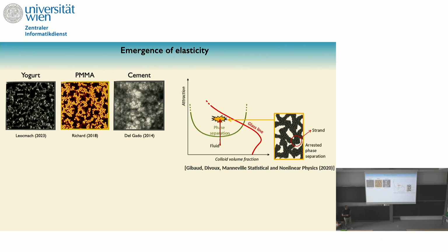Okay, so how would this system form? The common wisdom to understand how these gels, or this sparse network, would form is the following. You have many parameters that you can change in your experiment. For example, you can change the range of the attraction between the particles. You can also change the volume fraction of your particles. Thermodynamics will tell you that at equilibrium, you have a phase separating region. If you go inside this region, you expect that the system would phase separate into a denser phase and a low density phase.